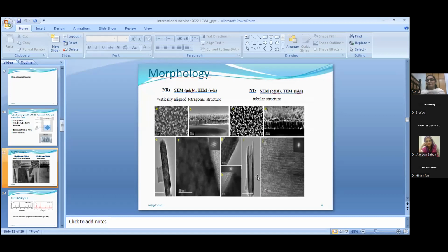Now moving towards I and J, these are the STEM images of the nanotube. As you can see, the edge part is affected, but the crystallinity of the nanotube is not affected in the core part. If we look at the TEM image of this edge part, we can note that the crystallinity of the nanotube is highly affected there, but it is not affected in the middle part.